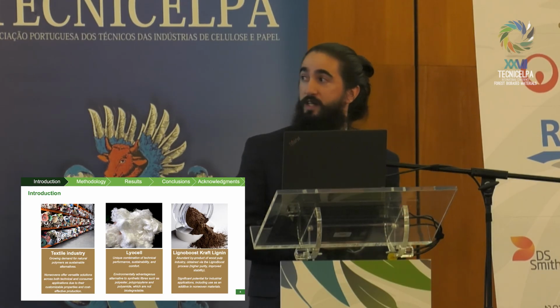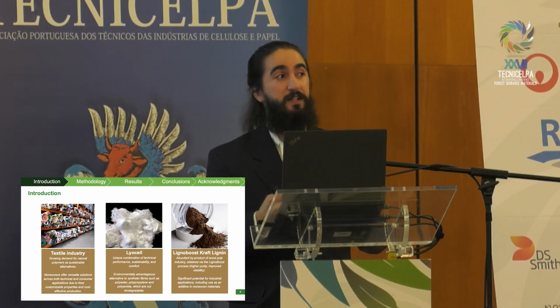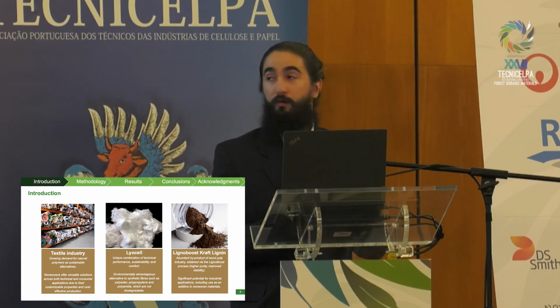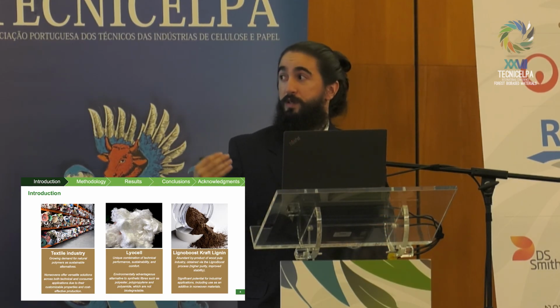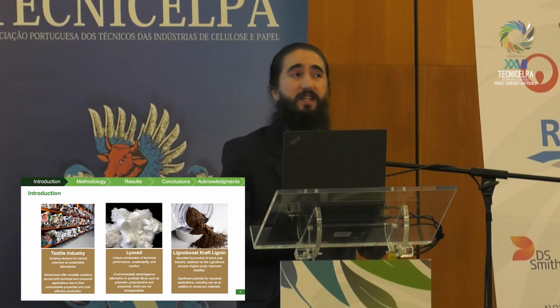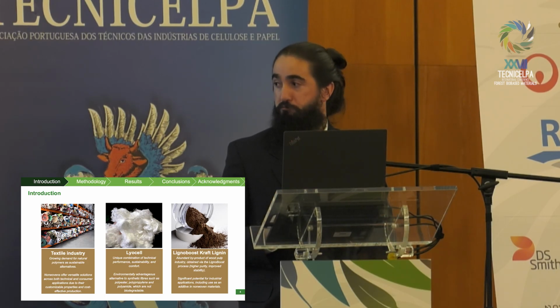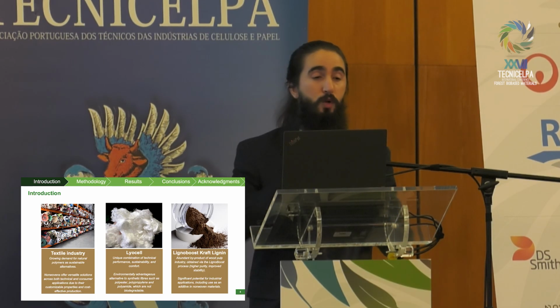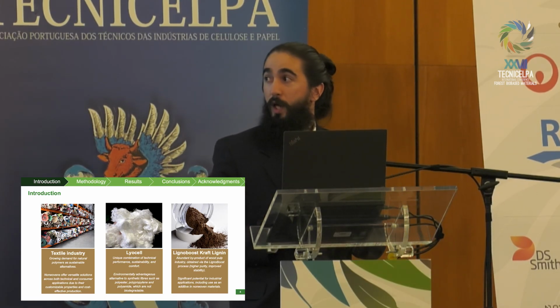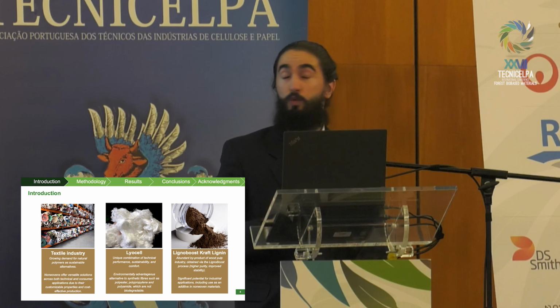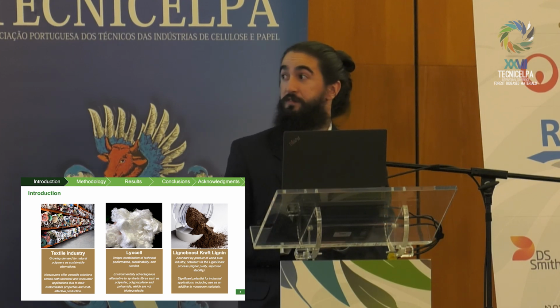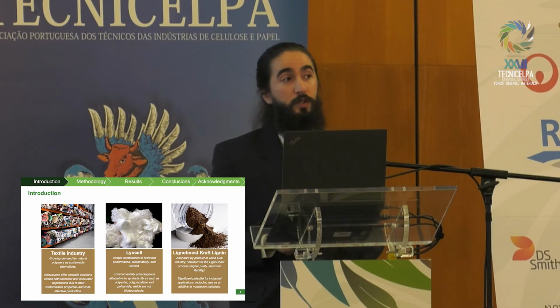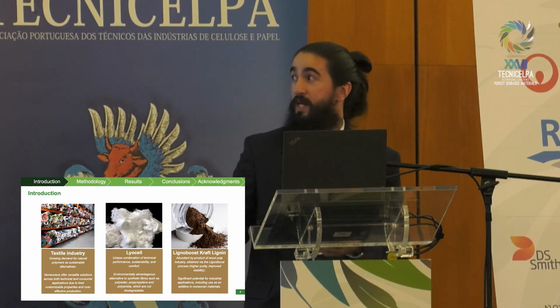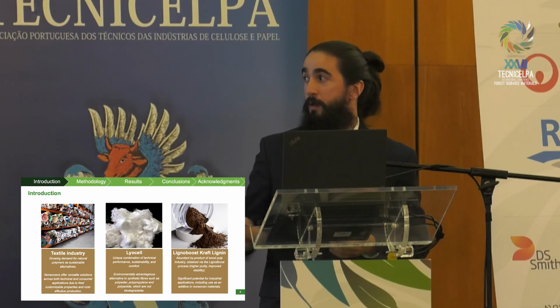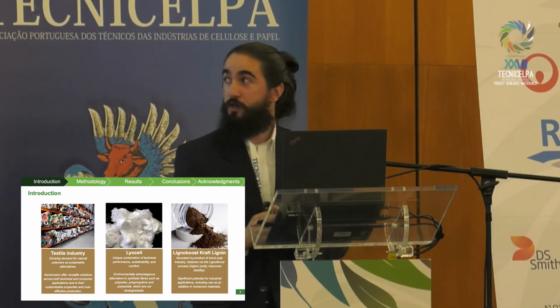Here specifically, we're going to talk about nonwovens. So they are not knitted or woven, but they are bonded using several methods. Before that bonding, we have a web formation that can be wet laid or dry laid, different strategies. And then the bonding can be mechanical, for example, needle punch, where we entangle the fibers. It can be also thermal, for example, spunbond nonwovens, and also chemical using some adhesives. The problem with these nonwovens is that they are mainly produced using synthetic fibers such as polyester, polypropylene, polyamide. So we wanted to take a different approach, using more sustainable fibers.